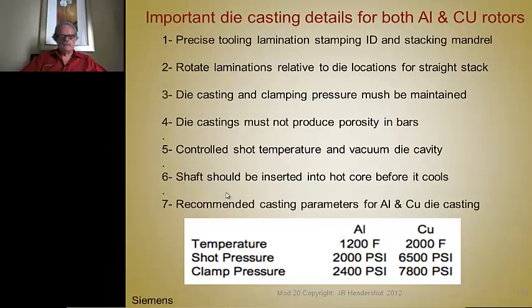And here's a list of the recommended pressures and temperatures used for die casting aluminum and copper. You can see that these are the melt temperatures required to get a good casting, 1200 degrees and 2000 degrees. So the copper's tougher. It's going to require different die materials because of that. Then the shot pressure, that's the hydraulic pressure used to shoot the molten aluminum into the cavity. And while you're doing that, you have to clamp the laminations together at a higher pressure than the shot pressure. So you can see there's quite a big difference for the copper.